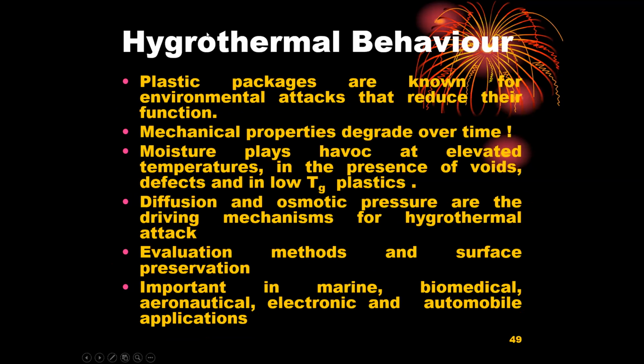Hygrothermal behavior. As we had already done the electrical to thermal and the thermal to structural analysis, we wanted to incorporate the influence of moisture attack at room and elevated temperatures. We know that plastic packages are known for environmental attacks. They are non-hermetic and they reduce their function. The mechanical properties degrade over time. Moisture plays a role at elevated temperatures in the presence of voids, defects, and in low TG plastics. So diffusion and osmotic pressure are the driving mechanisms for hygrothermal attack. Evaluation methods and surface preservation are the protective or control methods.